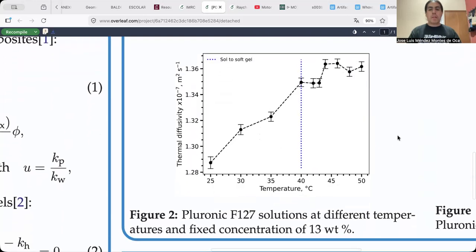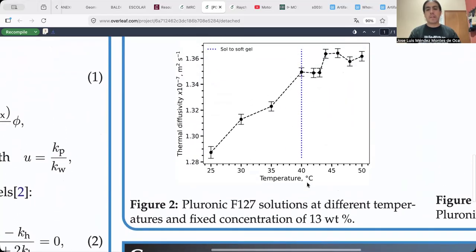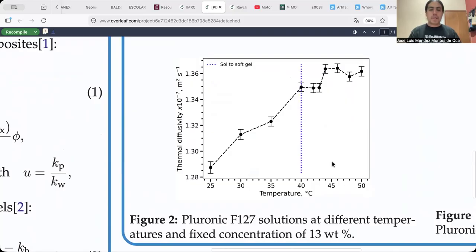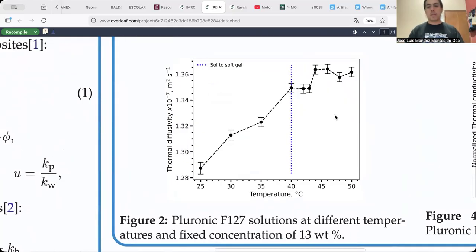We conducted another experiment with a fixed concentration of 13 weight percent of pluronic in DI water and upon different temperatures. And the transition from solution to soft gel is depicted as this blue dotted line, and a change in the slope of the curve is also observed.